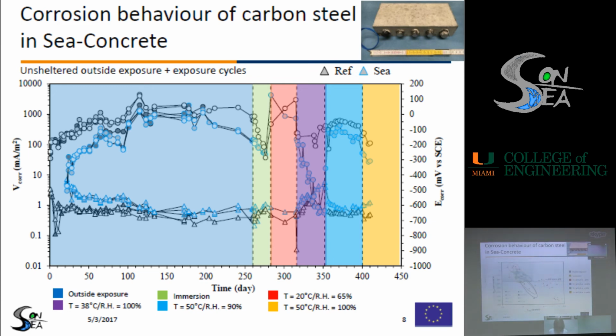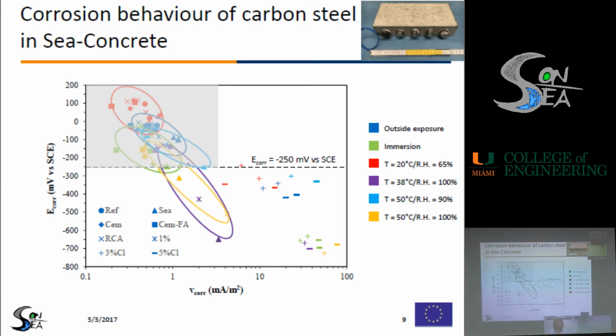This figure summarizes the results obtained on the carbon steel bar embedded in the different mixes, which are represented by the different symbols, exposed to the different environmental conditions, which are represented by the different colors. In particular, it shows the relationship between the corrosion potential and the corrosion rate. The gray area in the upper part of the figure represents the condition where carbon steel is passive.